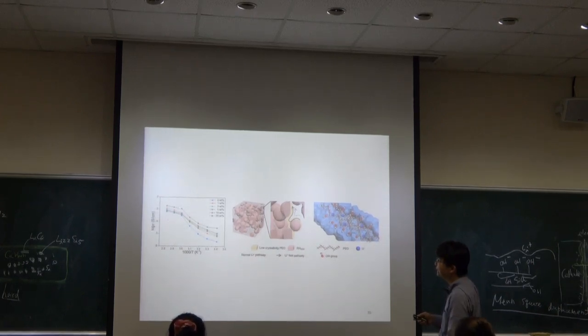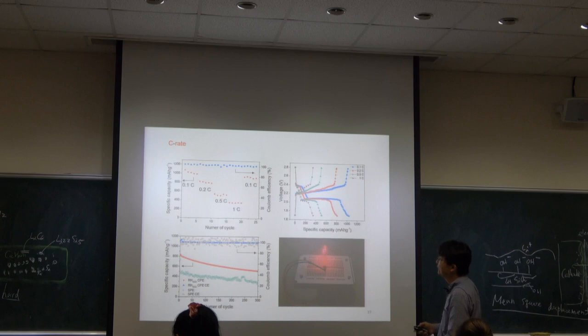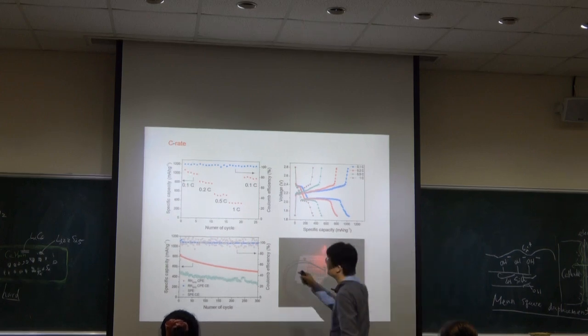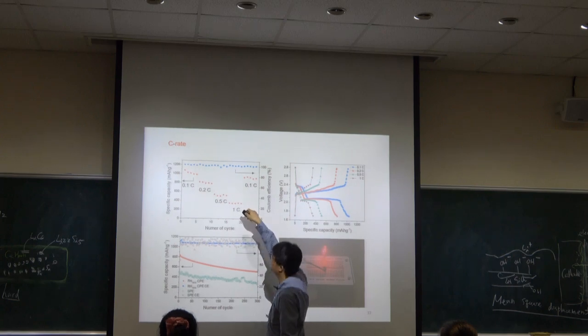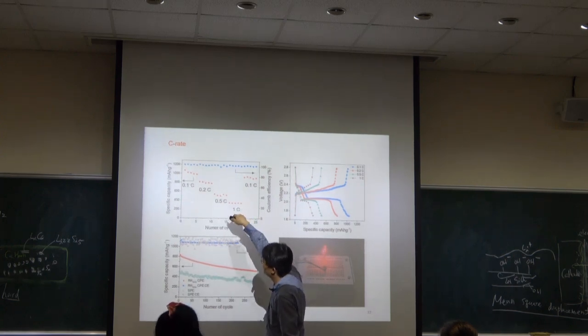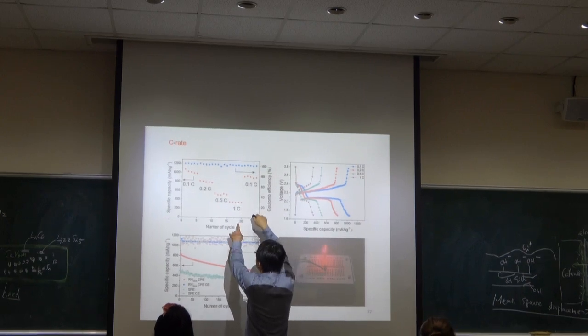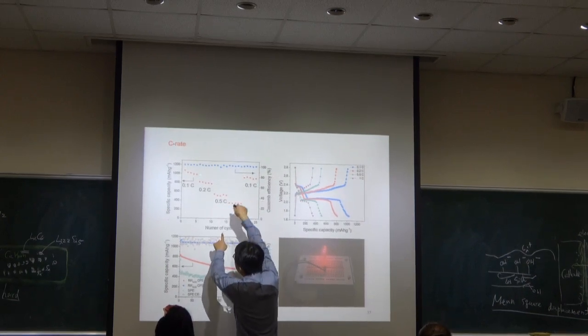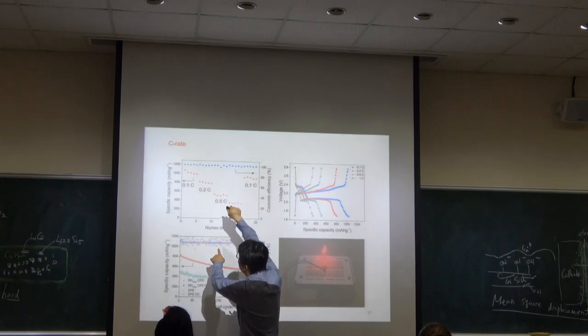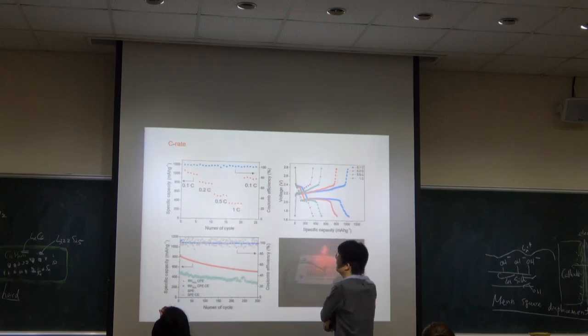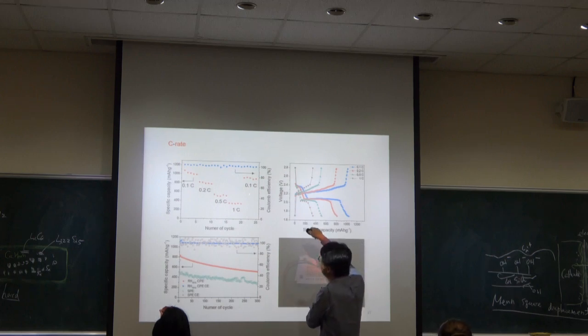So this is our calculation. We get the higher conductivity at 5% here at room temperature. Ideal conductivity can reach about 1.1 times 10^-4. So this is the C-rate charge, as I mentioned. This is 1C, and when we increase the charge rate, that means the current density, the capacity will be lower. But if we reduce the charge rate, we can still maintain quite the same. Capacity can reach 1,000. So this is quite reversible.